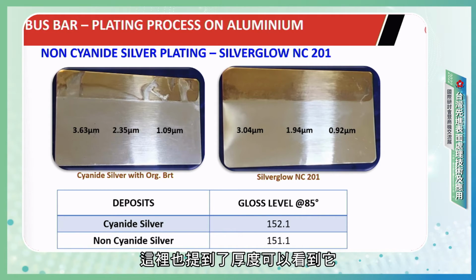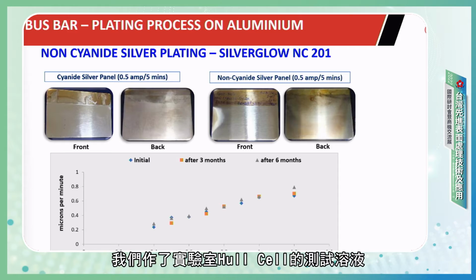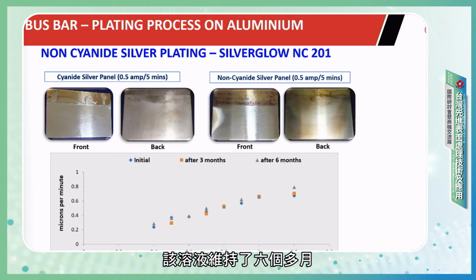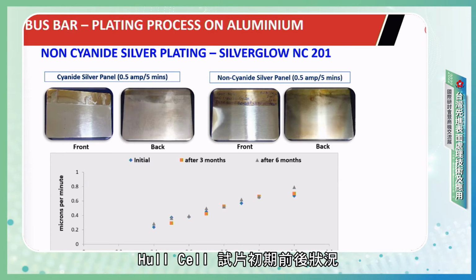Thickness is also mentioned here - you can see it's more or less in the same range as cyanide silver. What we have done here is a Hull cell test of a solution prepared in the lab, maintained for more than 6 months. From time to time we analyzed this thickness, and it's presented here along with the Hull cell characteristics. Now you see this is the initial, front and back side, and after 3 months, the front and back side.